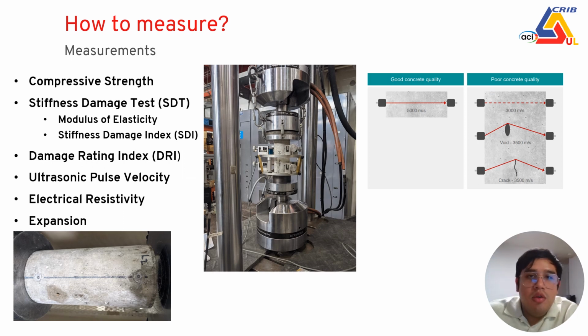When we talk about results, it's always at the beginning that the question appears: how to measure? The most important thing is that we already generate some damage in the concrete by the electrochemical treatment, activating the oxidation reaction of the sulfide-bearing aggregates, but we need to know how to measure this damage and if it's really contributing to decrease some properties of the concrete, and we need to evaluate how it's going to be affected. So we do some compressive strength and stiffness damage tests, which is small cycling testing on concrete specimens consisting of 5 cycles of compression and decompression of the specimen, and we can measure the modulus of elasticity and some other index.